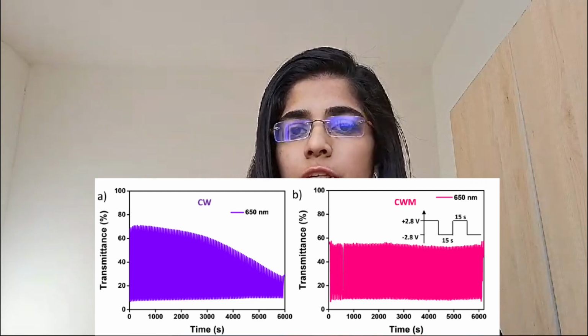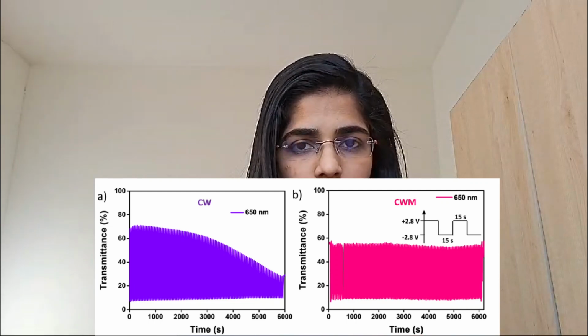Furthermore, the bilayered electrodes demonstrated exceptional stability across 200 cycles with virtually no reduction in optical transmittance contrast. The MnO2 overcoating forms a barrier between the WO3 films and the electrolyte and reduces the interfacial activation energy for charge transfer, enhancing the electrochemical stability.